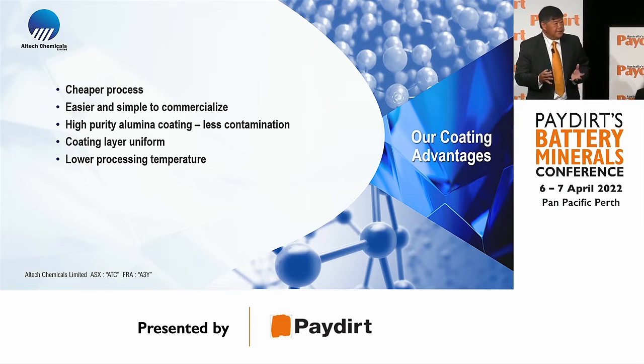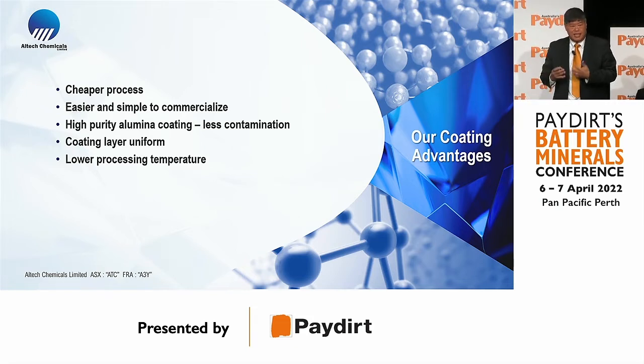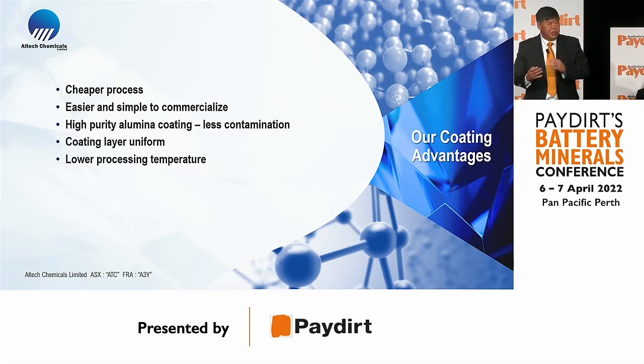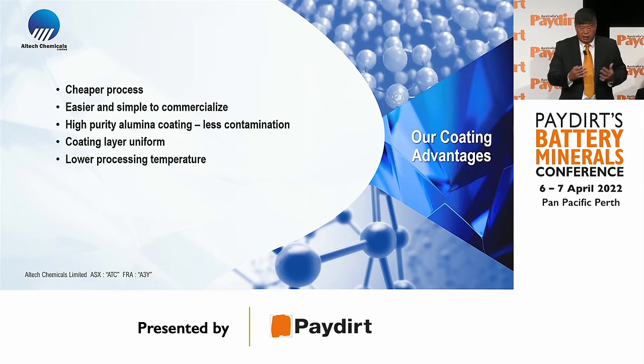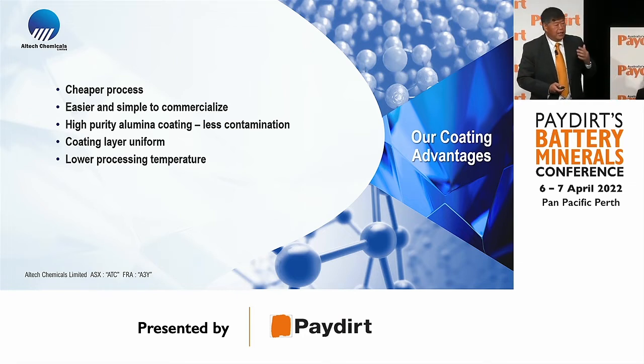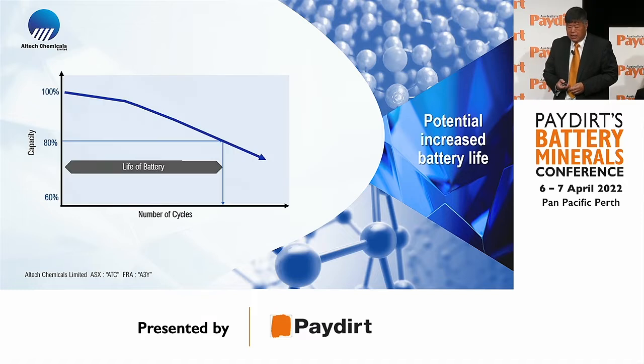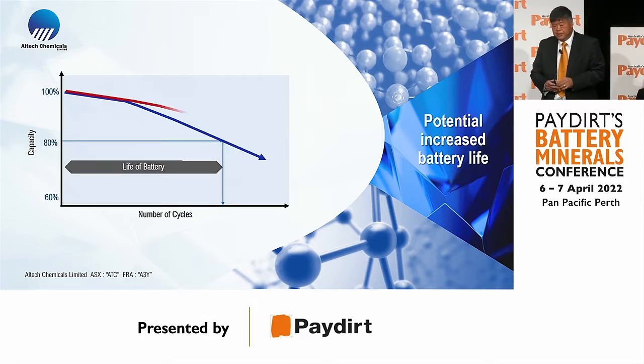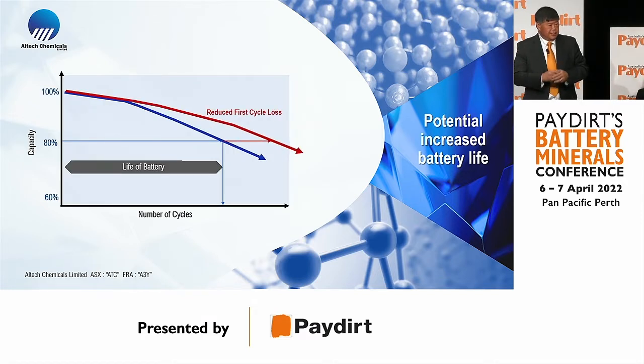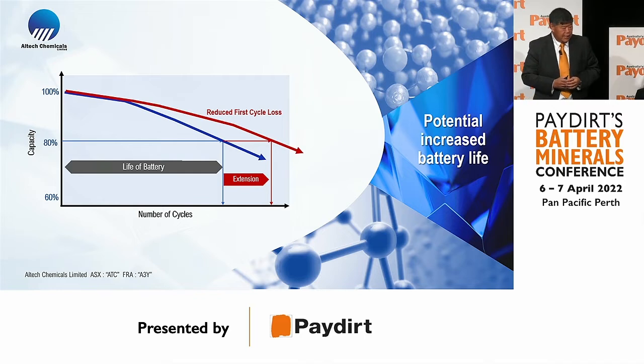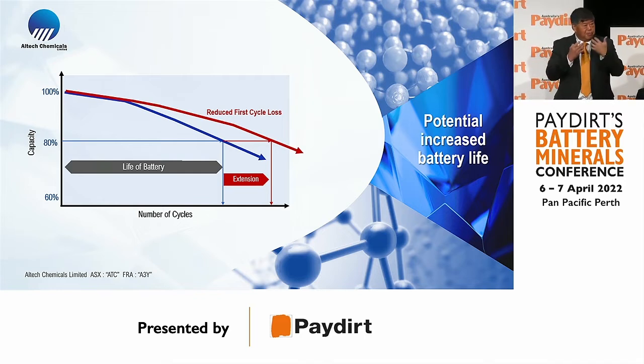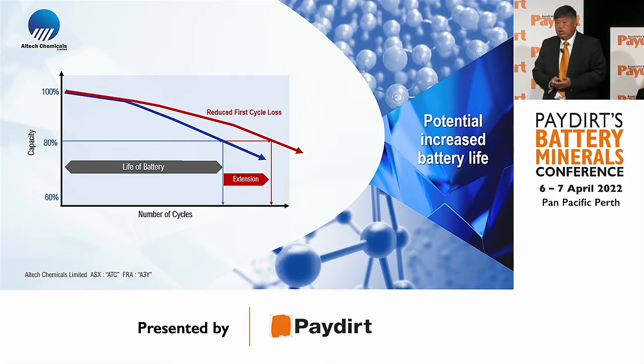So our process, we believe, is a cheaper process. It's easier to commercialize. And we use high purity alumina, which has less contamination. And we can adjust the coating of the material. And also because of our low operating temperature, as I mentioned, a lower cost of production. And what we're aiming for is something like this. This is a typical performance of a battery. If we can extend the life of the battery by leaving more lithium ions in the operation, you're going to get an extension of battery life.